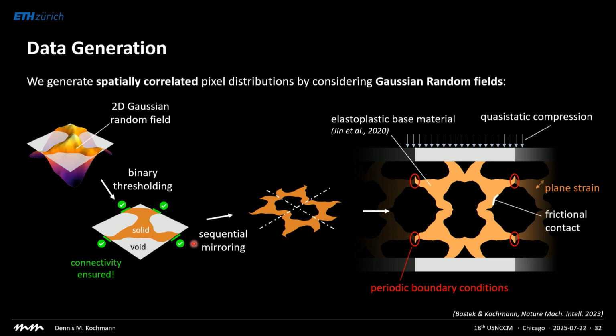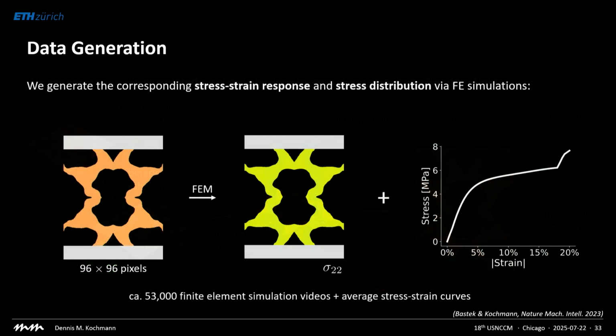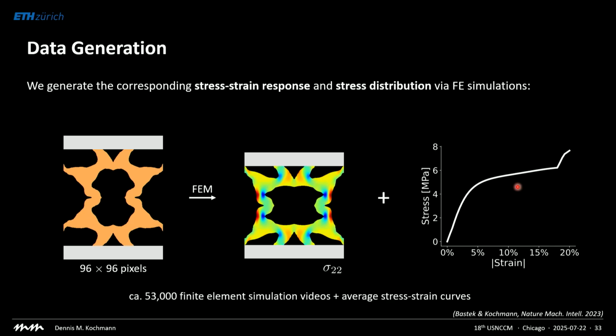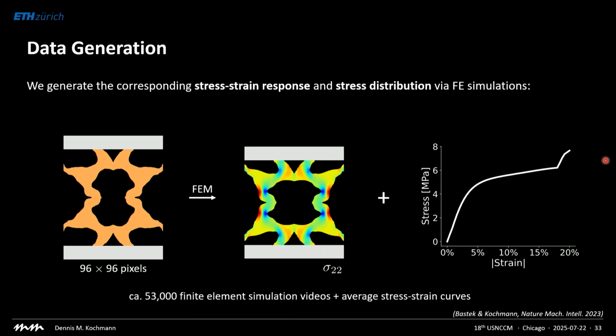And the simulation, we tried to make it as complicated as we can. This is an elastoplastic base material, including plasticity and failure, calibrated by 3D printed experiments. We introduce contact and friction, and then we simulate about 53,000 of these structures. And for every structure, we obtain a video showing the response with a color code highlighting, for example, the stresses, and we get the effective stress-strain response.